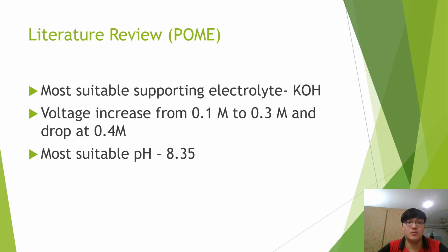According to the research, KOH is the most suitable supporting electrolyte in POME to treat polymer due to its highly mobile hydroxide ions. The voltage increases with the concentration from 0.1 to 0.3 molar but drops at 0.4 molar. And the most suitable concentration is 0.3.